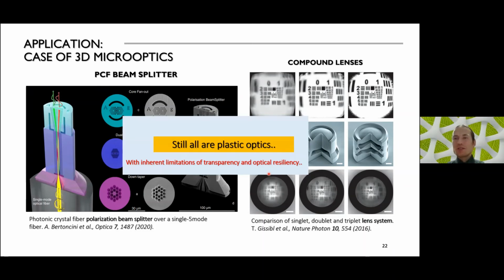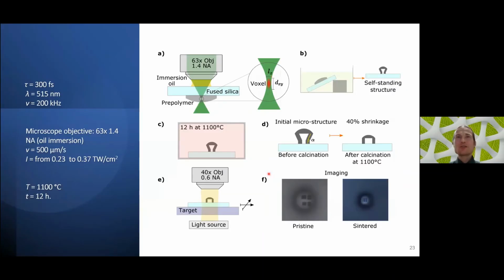And now I will merge what I have just spoken before with what I show here, applying the same technique and making the 3D structure with a material which we like due to its low shrinkage or no shrinkage, and by intentionally introducing some precompensation shape, we can make it shrink to get the position where expected, where it's wanted, by putting it on some sacrificial or support structures. And then it's already made an inorganic, glassy optical component, which can be characterized by its optical performance for both pristine and sintered material for imaging.